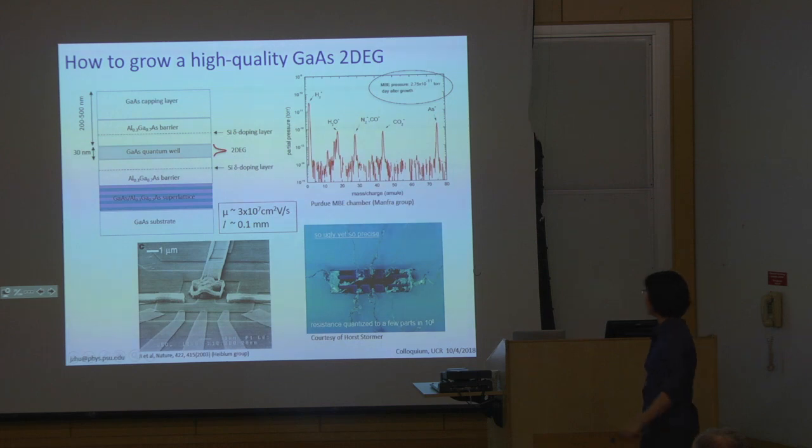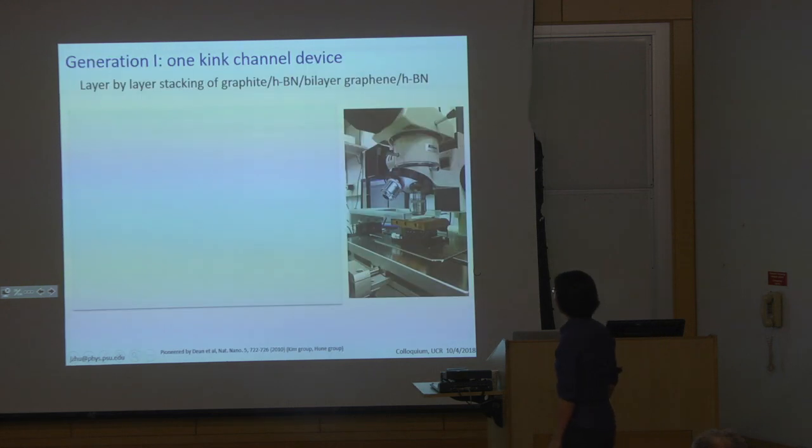So when you work in graphene, you don't need a collaborator like Loren Pfeiffer, who has an MBE chamber, to grow it for you. You just get a piece of HOPG graphite and start exfoliating, and your lattice is perfect. There's no defect whatsoever. So this really makes a level playing field. What we do in our lab, and many people do here as well, is use a technique pioneered by groups at Columbia, Philip Kim and Jim Hone, to stack graphene and insulator, this hexagonal boron nitride I mentioned, and use it as a protecting layer and a dielectric layer to gate our graphene samples.